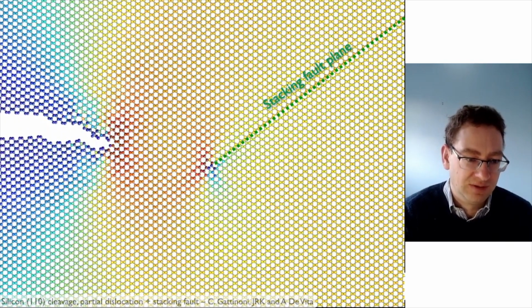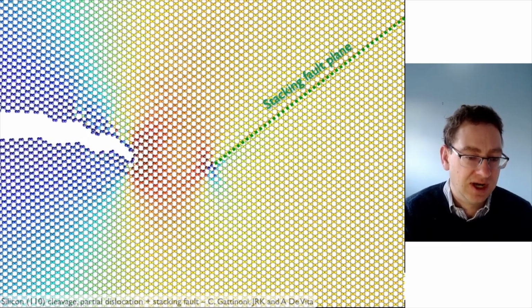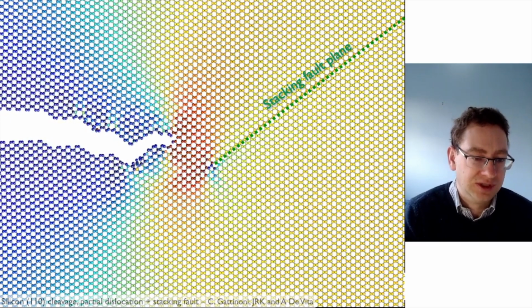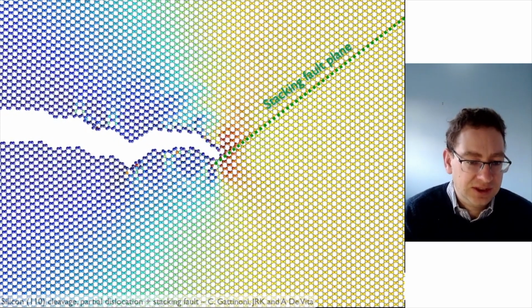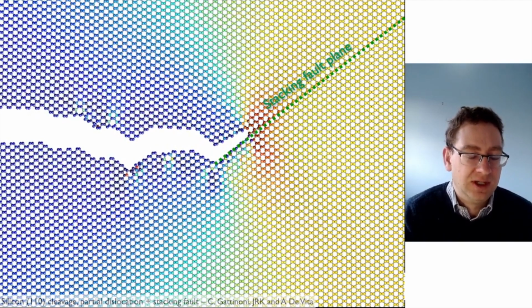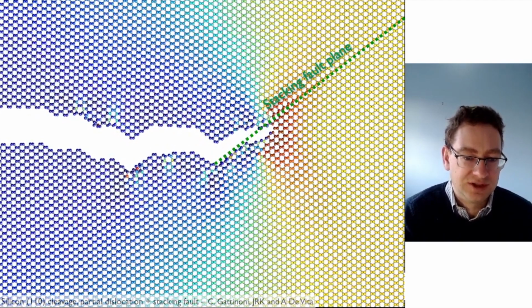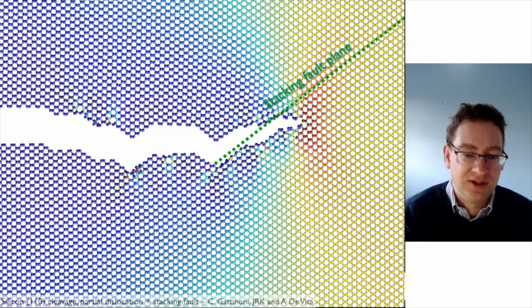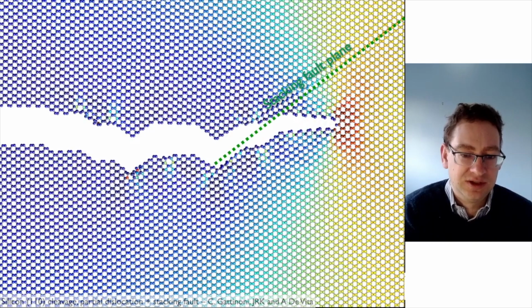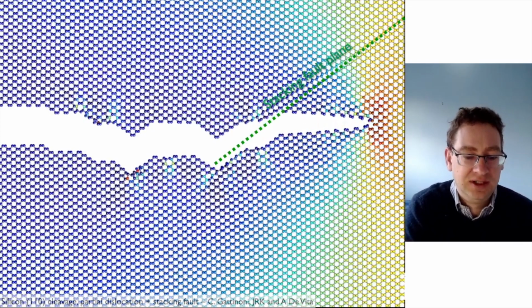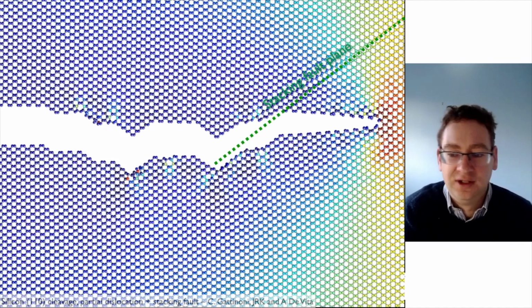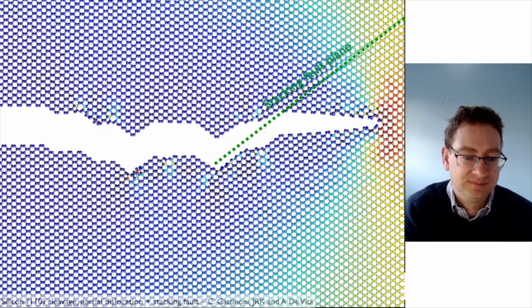So this is a good example. Here I've got a crack tip that is running around and being driven towards a dislocation. So I've got both types of defect in this material, a crack and a dislocation. And what we see actually is that the crack gets pulled down towards the dislocation core, and then eventually it annihilates the core, it makes it go away, and then takes a diversion up the stacking fault, which is a weak plane, weak interface in the material. So here we're using the computer to really predict what we would expect to see in reality if we were able to zoom in this far and take pictures very quickly.